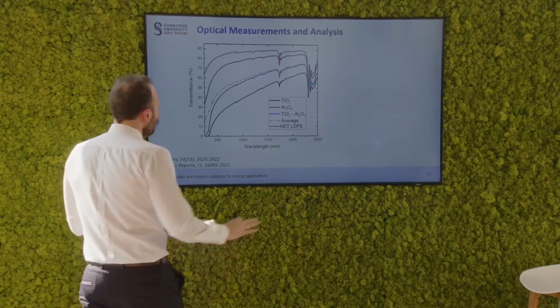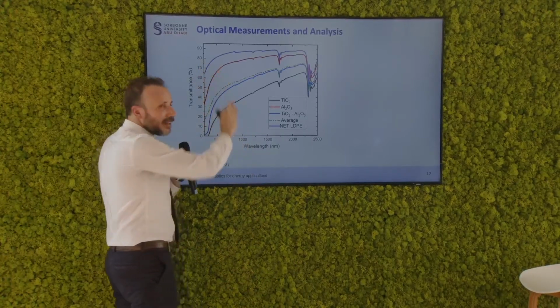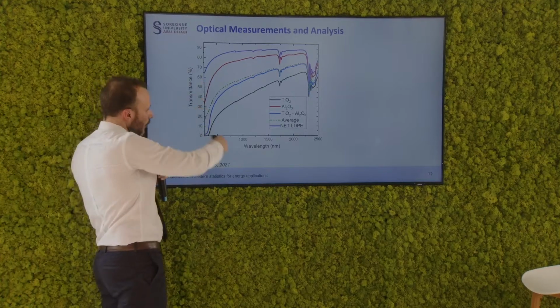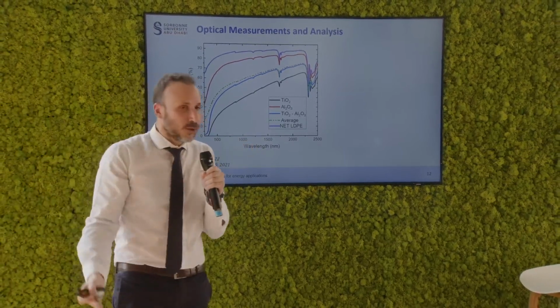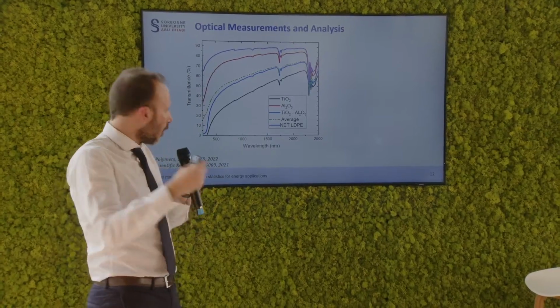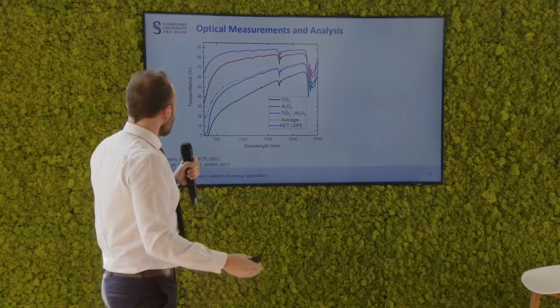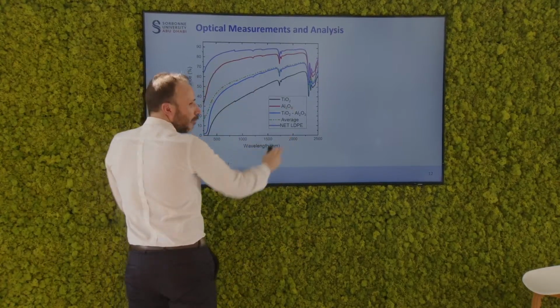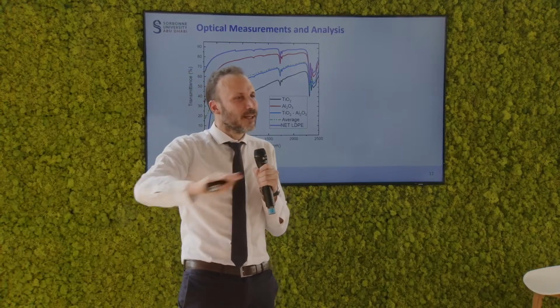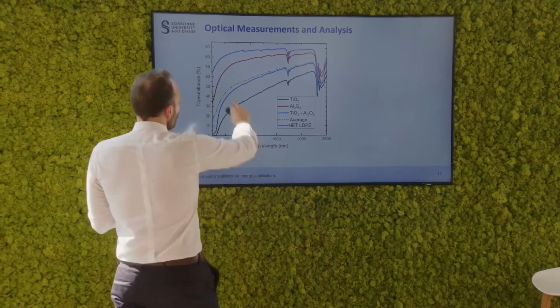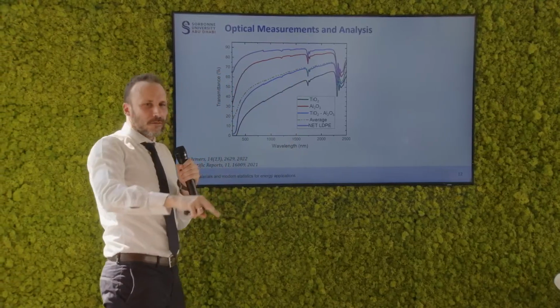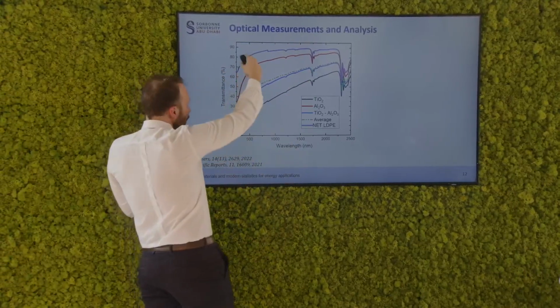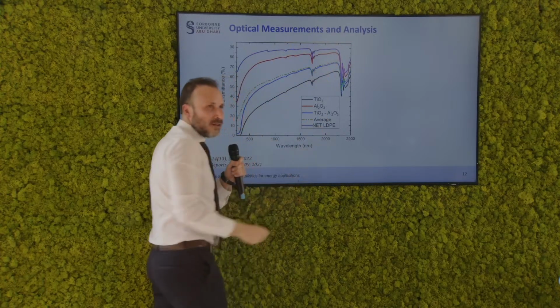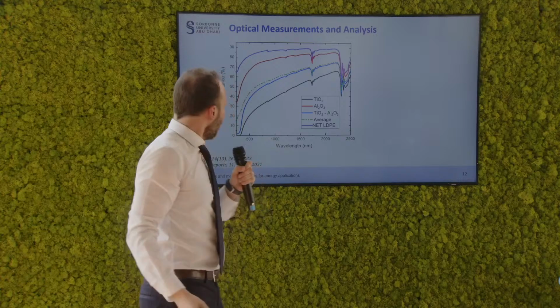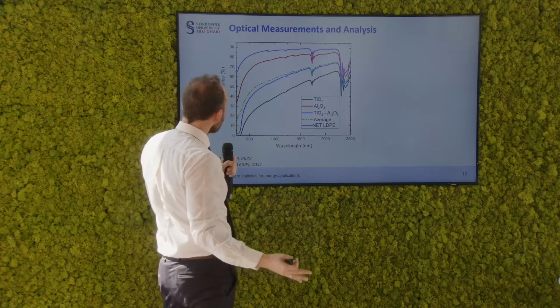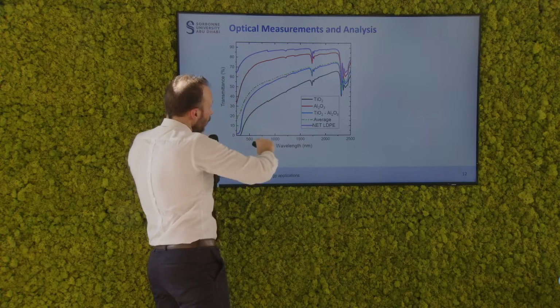So the first thing we need to do here, when we take our films, is optically characterize them. In this graph, I have the transmission and the wavelength to see how much light is passing through the film according to the wavelength of the radiated light. So, as you can see, the net LDPE film, which means it's only the polymer, we have not included any of the nanoparticles, allows a huge amount of radiation to propagate through it. So you see, even in the UV region, the visible region, and the infrared region, all the light is allowed to pass through.